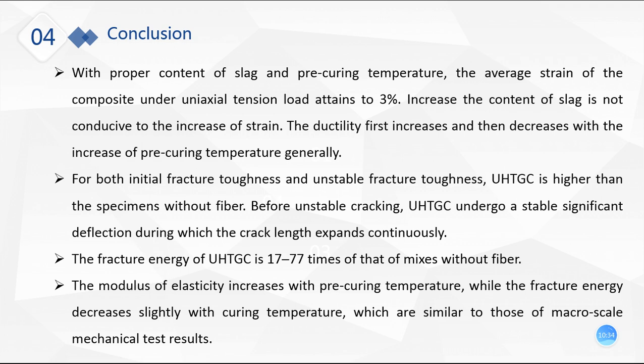Before unstable cracking, the specimens undergo a stable significant deflection during which the crack length expands continuously. The fracture energy of UHTGC is 17 to 77 times that of mixes without fiber. The modulus of elasticity increases with pre-curing temperature, while the fracture energy decreases slightly with curing temperature, which are similar to those of macro-scale mechanical test results.